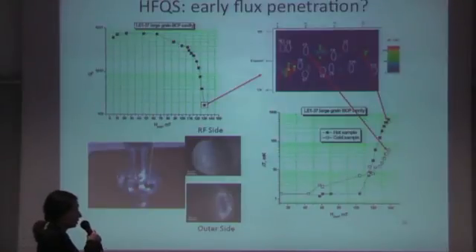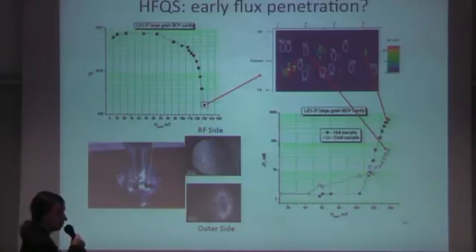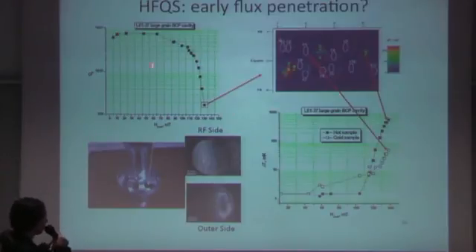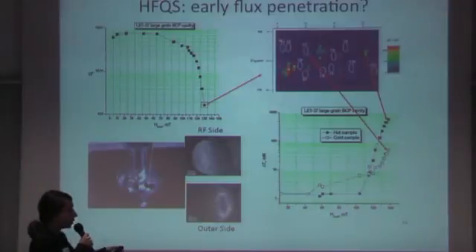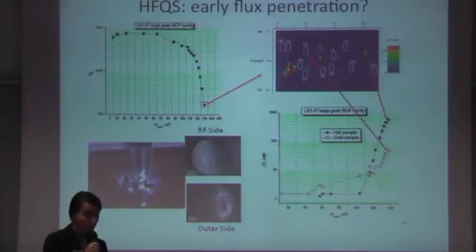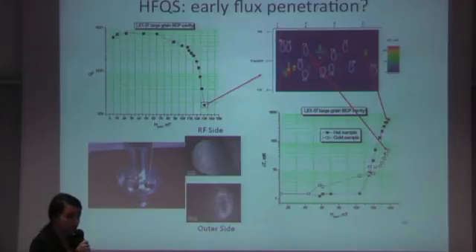So this is what we want to do — try to prove it once and for all. We take high-field Q-slope limited samples cut from a Cornell cavity: large-grain BCP cavities that exhibited high-field Q-slope. The cavity was studied with thermometry and then cut at different spots — we have hot spots and cold spots. We want to take these hot and cold spots and, since we know the onset of high-field Q-slope from the RF measurements, ask: can we correlate this onset with the field of first penetration measured with µSR?